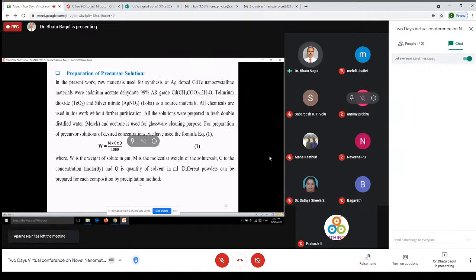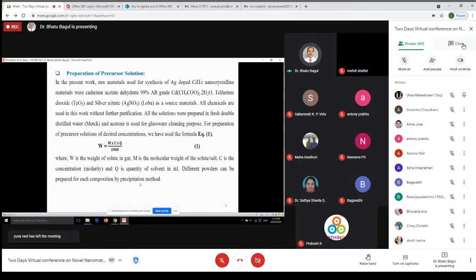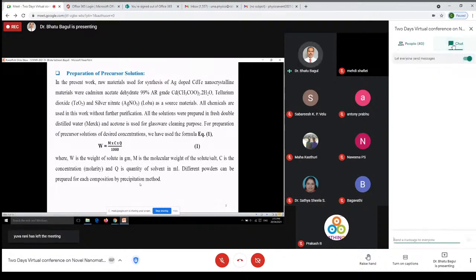Now, how the precursor solution is prepared. In the present work, the raw materials used for the synthesis of silver doped CdTe nanocrystals are cadmium acetate dihydrate, 99% AR grade, tellurium dioxide TeO2, and silver nitrate AgNO3 from LOBA as source materials. All chemicals are used in this work without further purification. All the solutions were prepared in double distilled water, and acetone is used for glassware cleaning.